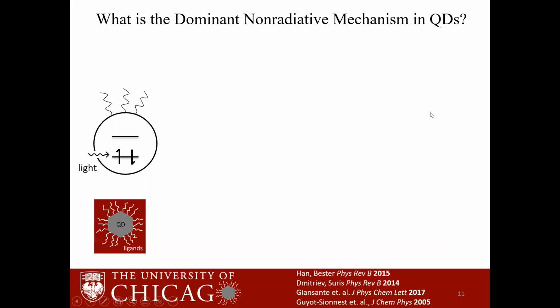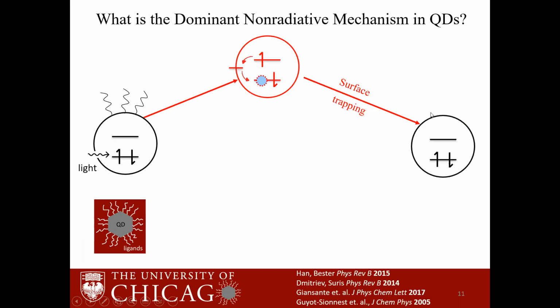So in this slide, I will talk to you about 3 common relaxation mechanisms for quantum dots. In this cartoon, I have these squigglies on the top, which are organic ligands, which are molecules which are bound to the quantum dot surface to stabilize them. In the first relaxation mechanism, which is called surface trapping, there are defect states on the surface of the quantum dot to which the electron or the hole will get trapped, after which it relaxes back to the ground state non-radiatively. For quantum dots emitting in visible and near-infrared wavelengths, surface trapping is the dominant mechanism. The remaining 2 mechanisms are more common for quantum dots in the infrared wavelengths.